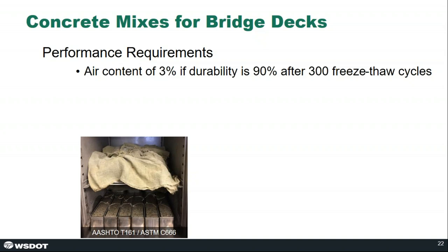So our performance specs include a requirement for air content or freeze-thaw durability. A contractor can propose a mix that has the air in the 4.5% to 7.5% range, but we allow them to drop that air content as low as 3% if they perform freeze-thaw testing and the mix performs with at least a 90% durability factor after 300 freeze-thaw cycles. The photo on the bottom there shows some of these specimens that will be subjected to freeze-thaw action. So this allows the contractor, in theory, to play around with the air content to achieve our target durability without compromising other properties.